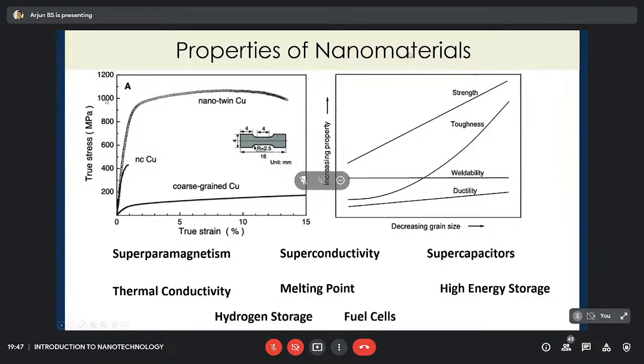This is basically a stress-strain graph, and this coarse-grained copper is basically the copper that we see in everyday life. You can see it is highly ductile. We can go up to say 15% strain without creating too much stress. However, if you want extremely high strength copper, we can use a nanoparticle-based copper material, which has extremely high strength.